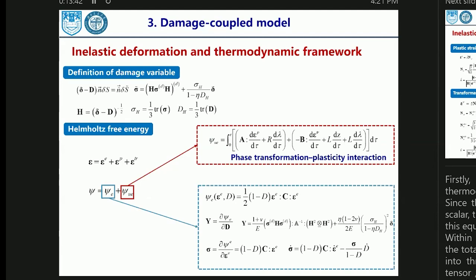And then we can see the damage coupled model. Firstly, the inelastic deformation and the thermodynamic framework should be introduced. This is a basic elastoplastic framework, and for a given state, the Helmholtz free energy can be divided into the elastic one and the inelastic one, and we can derive the stress and strain, elastic and damage relations. Most importantly, we introduce the phase transformation and the plastic interaction in this free energy.